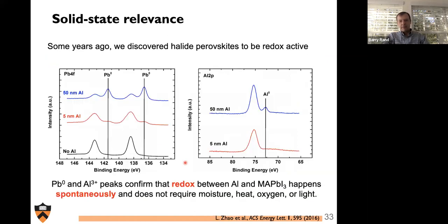A final couple points I'd like to make is that this work does have solid state relevance as well. Many years ago, this was work published in 2016, we discovered that halide perovskites were exceptionally redox active. This work was exceedingly simple in that we mated lead halide perovskites with a readily oxidized metal, in this case, aluminum. And what we found was a spontaneous metal cation redox reaction, whereby deposition of aluminum on top of the lead halide perovskite resulted in formation of lead 0 and formation of aluminum 3+.